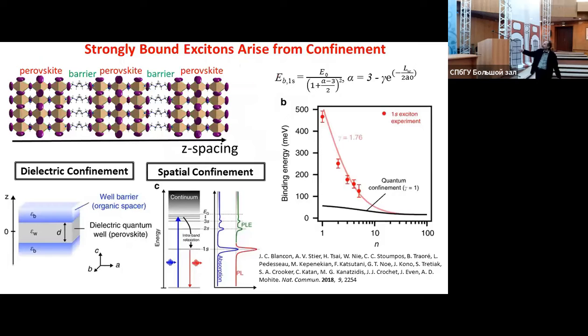There is work by our colleagues in Los Alamos who studied extensively the evolution, the effect of quantum confinement. It's not a simple quantum confinement. There is a very significant contribution from the dielectric contrast between the organic and the inorganic part. So we found an equation that may or may not hold. I just wanted to stress that these materials have huge binding energies, and we're talking here about room temperature measurements, all these measurements at room temperature. This is something that intrigues us and we try to understand it better.